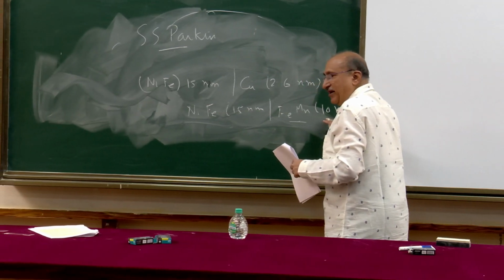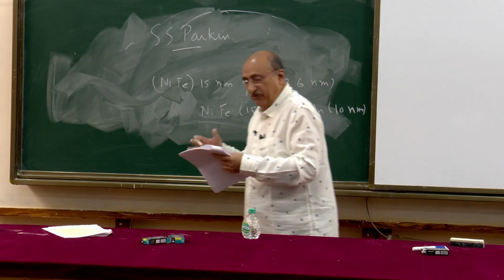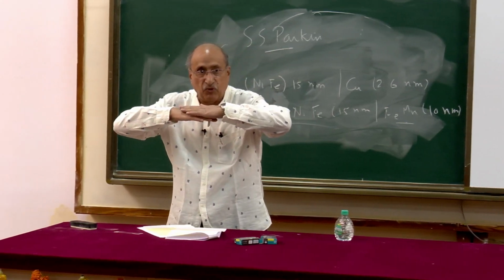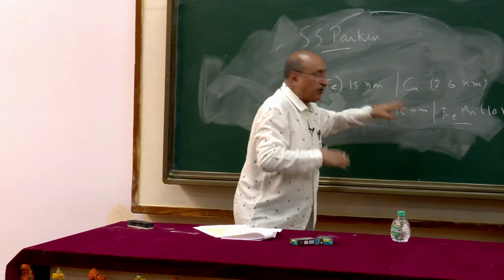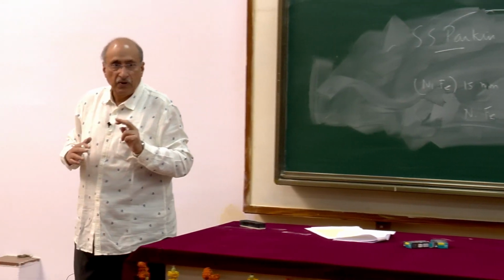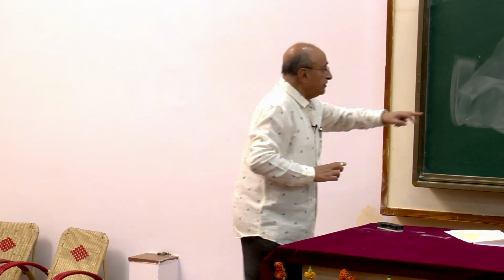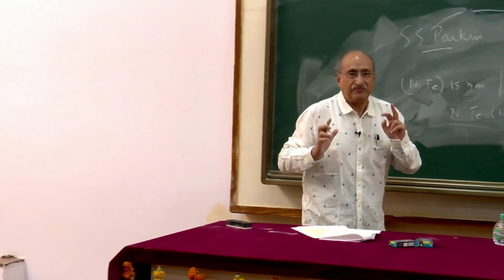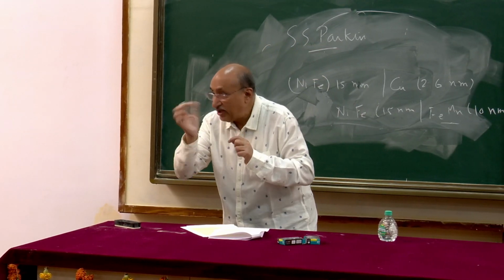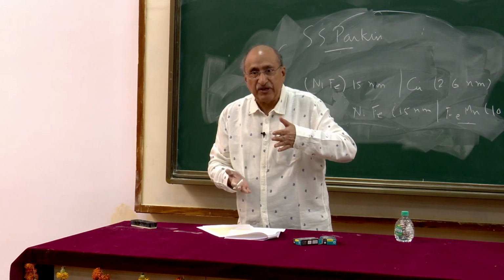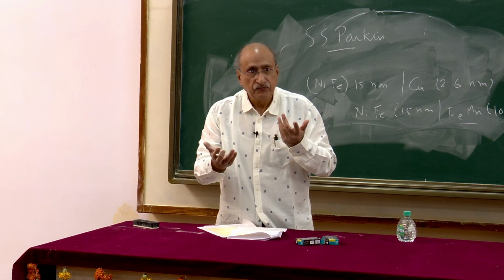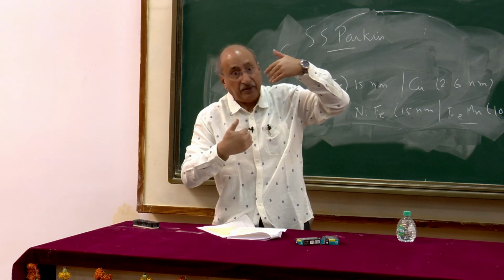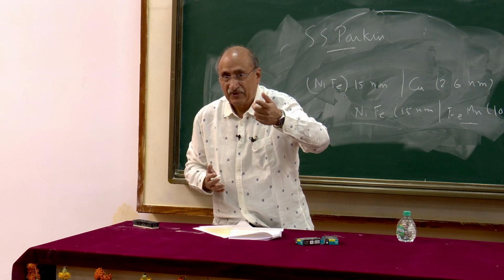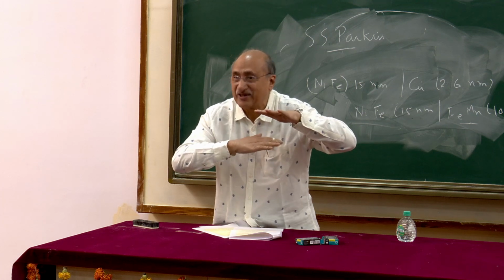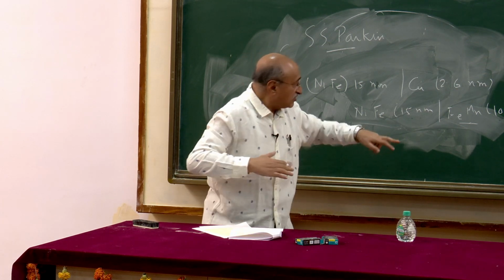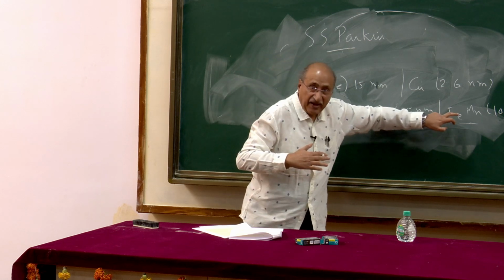Closer to one layer is iron manganese, which is an antiferromagnetic material and creates an anisotropy which holds the magnetic moment, effectively increasing the coercivity of this particular layer. So when I apply a field, the other layer will switch, but not this. If I want to switch only one of the layers, and both of them are of the same material, if I apply a field, both will switch together. You don't want that, because I want it to be either parallel or anti-parallel. So I want only one of them to switch, so I must hold this one by increasing its coercivity. This coercivity is artificially enhanced by putting iron manganese.